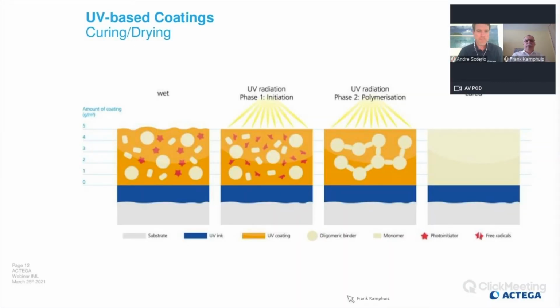To dry a UV coating, a UV-based coating, it's a curing. That means you have the liquid film, and with UV light, you have a chemical reaction, a polymerization, and then you get the cured film. That means if you apply a 100% liquid film, you get a 100% cured film. If you apply 5 grams per square meter, you get 5 grams per square meter.